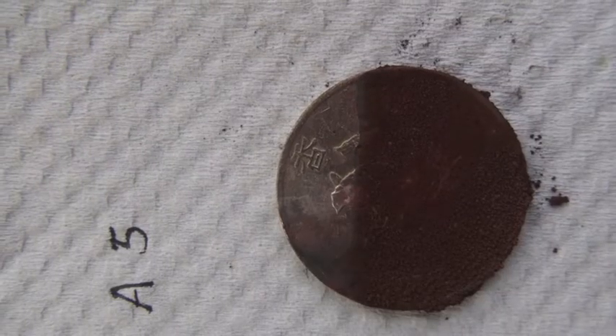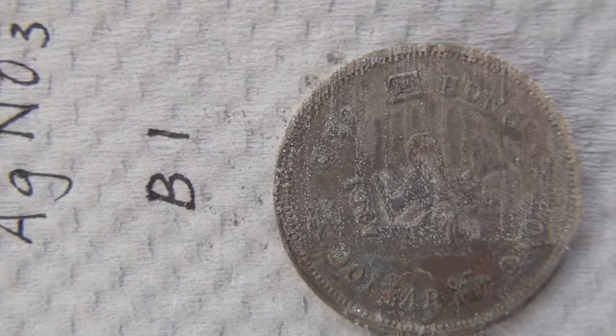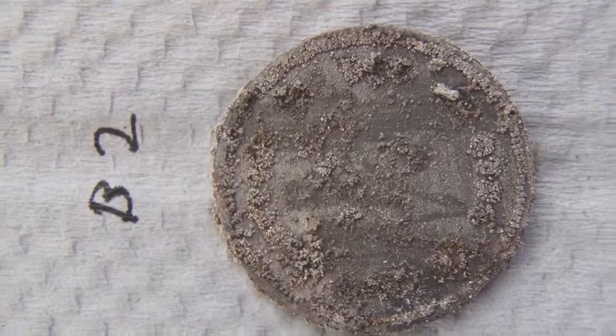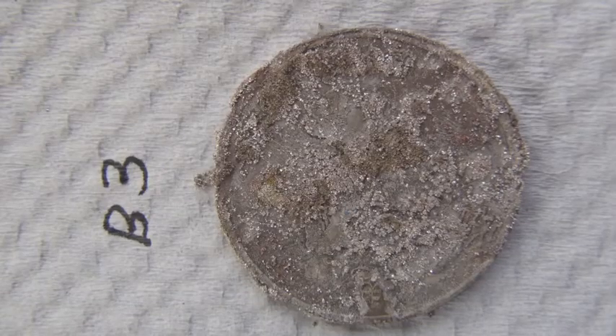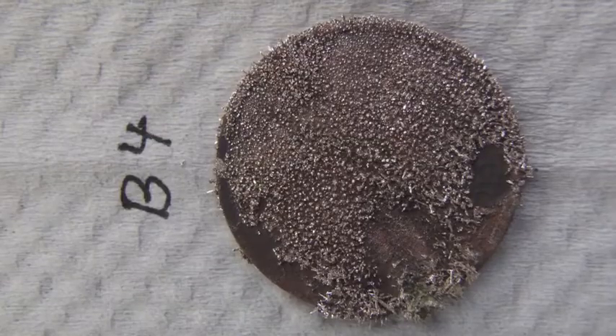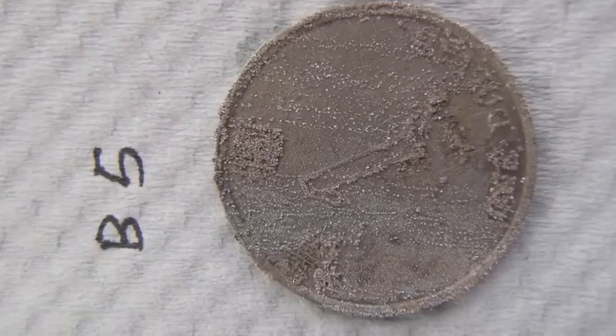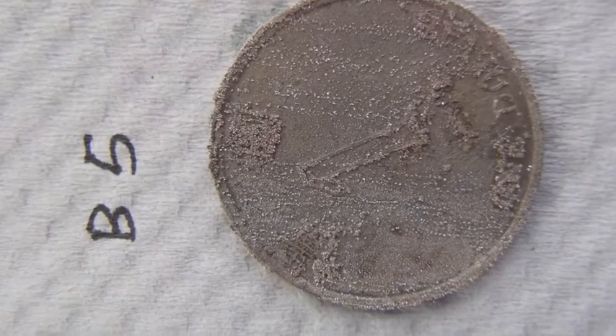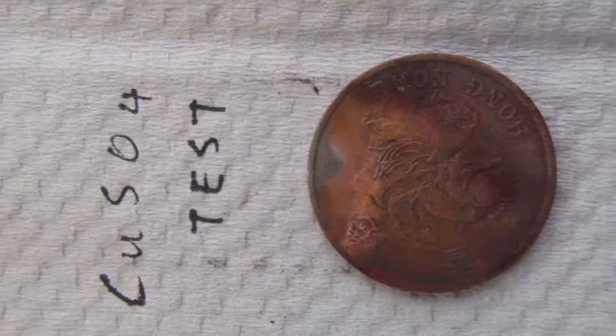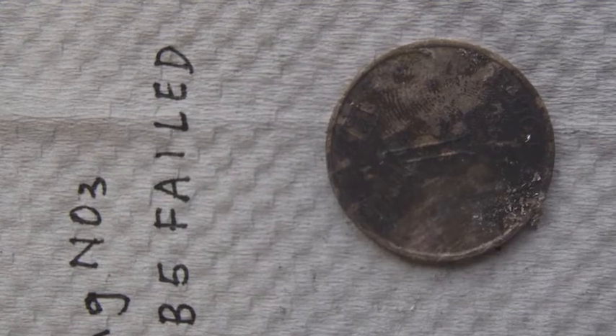This shows that electroplating requires a great source of energy, and since this reaction is constantly used in mass proportions in many different fields of production, the energy use is also very high. In our experiment, we discovered that even though coins charged with greater amperage may gain a thicker layer of metal coating, it was very brittle and detaches from the coin very easily. On the other hand, the ones with the lower amperage have more ideal results. However, the lower amperage requires a longer time for the object to be entirely covered with a layer of metal.